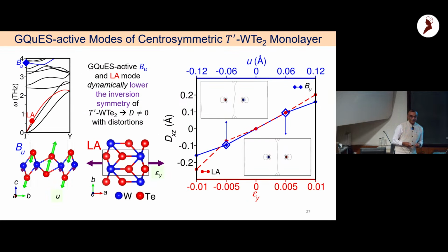So let me first show you an example. This is a centrosymmetric tungsten telluride monolayer, which shouldn't show any nonlinear Hall effect of the kind I explained. There are two phonons I'm pointing out in this phonon spectrum of the monolayer. One is the optical B_u phonon, and one is the LA phonon, the longitudinal acoustic mode, which essentially is a strain wave in the crystal. What we show is that both of these phonons are active in what we call GQUES spectroscopy, and basically the Berry curvature dipole becomes non-zero the moment you freeze in these changes in the structure associated with these vibrations or the strain mode.